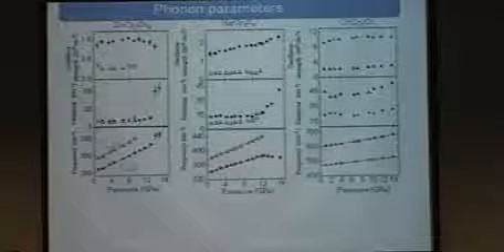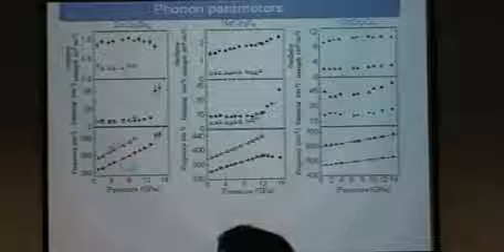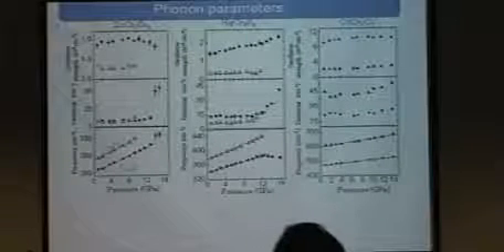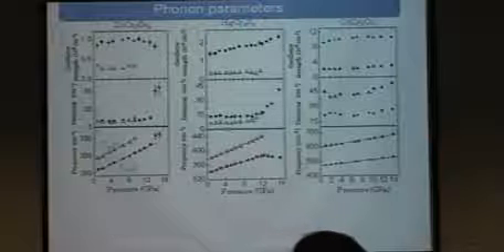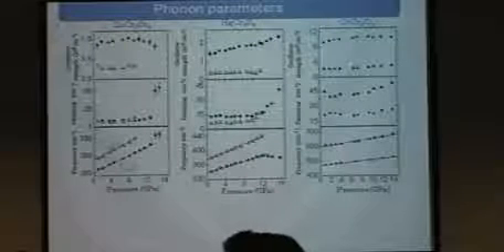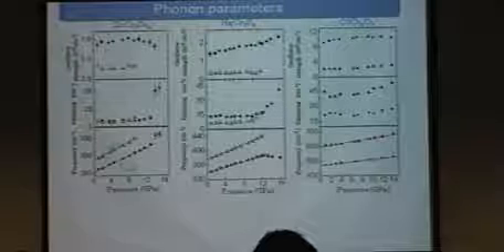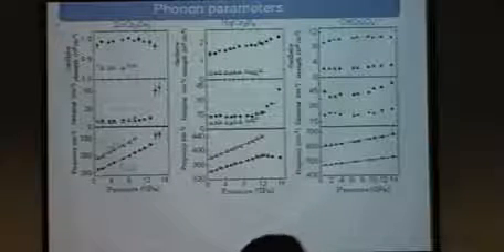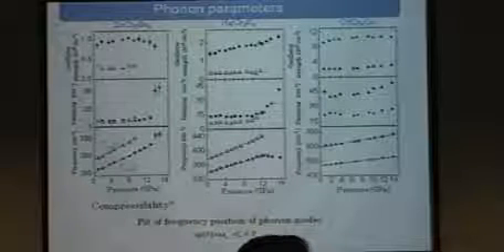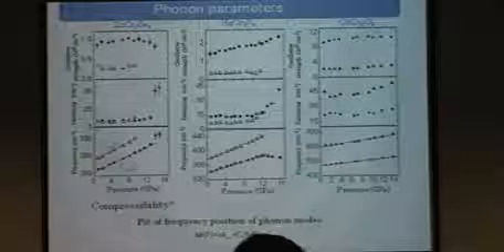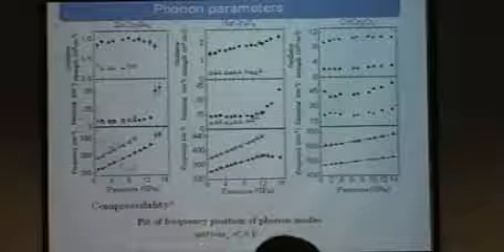Okay, and here are the phonon parameters extracted from the fit of reflectivity by a simple Lorentz model. You see the frequency, damping, and oscillator strength. When you see the infrared data, the oscillator strength of the phonon modes tells the ionicity of the bond belonging to that particular phonon mode. So the higher the oscillator strength is, the more ionic the character of the bond belonging to that mode. And to see the compressibility of the phonon modes, I fitted the frequency position by simple linear equations, where omega naught is the frequency at ambient condition, delta P is the change in pressure, and C is the linear pressure coefficient.